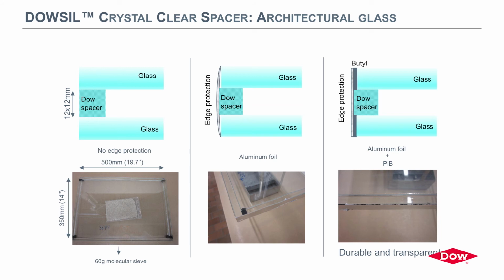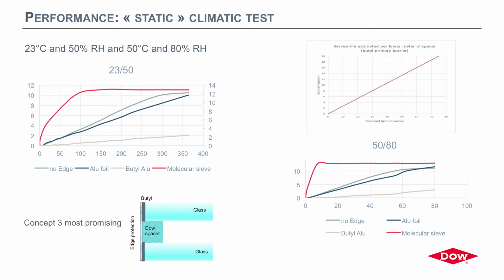And then in the third step, and that's really our concept today, we inverse the order of the secondary seal and the primary seal. So the butyl is applied on the edges of the glass. The Dow spacer is just protruding 1 millimeter, and so everything is aligned. And then you have the metallized foil on top of it. This foil is sticking to the spacer with the primer, and the butyl is also sticking to it. When you look at it in the face, you see a very clean edge with just a tiny black line. So that's our concept, and we have now performed internally what I call a static climatic test.